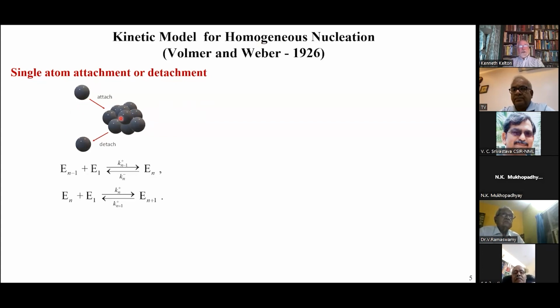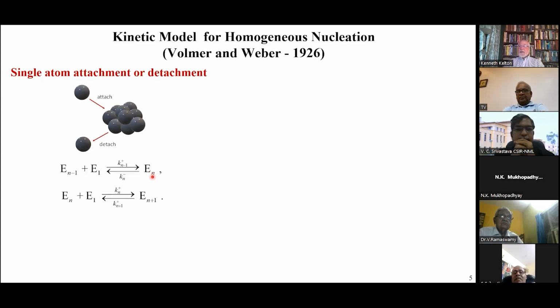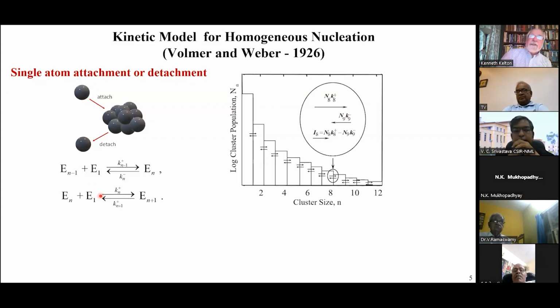They said that this occurred one single atom at a time, and so they expressed this in terms of rate equations, where a cluster of size n-1 has a single atom join it, and with a forward rate constant it becomes a cluster of size n, one larger. But then it could also leave the cluster and go back to the original cluster plus the single monomer. They developed this for every single cluster, so what you end up getting is a cluster population. Here's an illustration: the log of the cluster population as a function of cluster size. You have different populations for different clusters, and generally the population decreases as you go to larger cluster sizes. From here, the nucleation rate is the flux past a given cluster boundary.